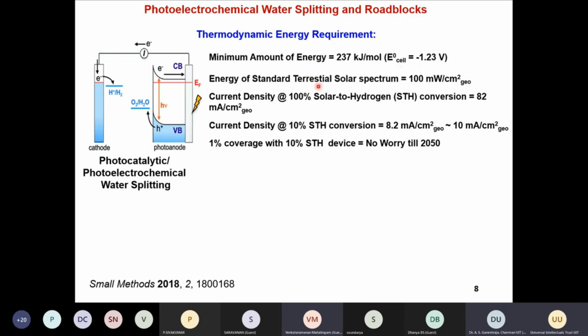The energy of the standard terrestrial solar spectrum is about 100 milliwatt per centimeter square. So the current density at 100% solar to hydrogen conversion is roughly about 82 milliampere per centimeter square. The current density at 10% solar to hydrogen efficiency is roughly 8.2. We take roughly 10 milliampere per centimeter square as a benchmark, which I'll be showing in my slides. But it's just a convention. Suppose you have 1% coverage with the 10% STH device, we will not need to worry for the next at least 2 to 3 decades. But the problem is the present status is roughly 1%.